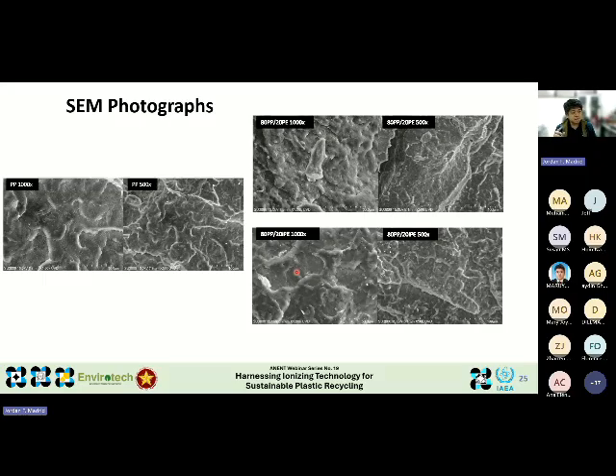When we look at the pure polypropylene sample, we see that its surface is relatively smooth compared to the blends. If you look at the polypropylene HDPE blends, whether 90-10 or 80-20, they show more complex surface features. For example, we observed hollow indentations and spherical protrusions, often referred to as core-shell or core-skin structures.